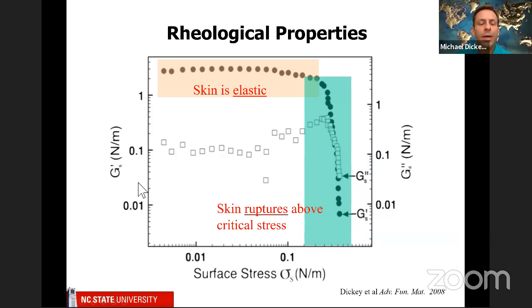And so what you'll see is that, just sort of like Hooke's law, this is a material property: the oxide skin is elastic, and so it's got this modulus, and then suddenly, if you push too hard, boom, it breaks. And so if you kind of trace this down, you'll see that it breaks somewhere around 0.3 to 0.5 newtons per meter. So that's like a really large surface tension if you want to think about it in terms of a physical force.